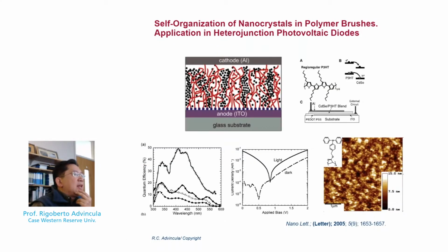Now, another example here is that a polymer surface can also have an electro-optical function. Here is the case of a polymer brush which contains a hole transport material such as this triphenylamine, affecting the bulk heterojunction properties of a polythiophene and a cadmium selenide nanoparticle on a heterojunction device. So in this case, the structure of the polymer brush has a big influence on the hole mobility or transport of these charge carriers at interfaces, hence affecting its performance, let's say, as a photovoltaic diode. So these examples I've shown you are some of the peculiar uses of a well-defined polymer brush, whether it's at the interface, an electrode surface, or controlled wetting behavior.